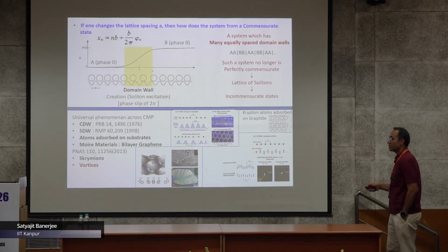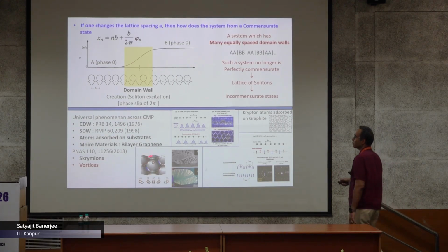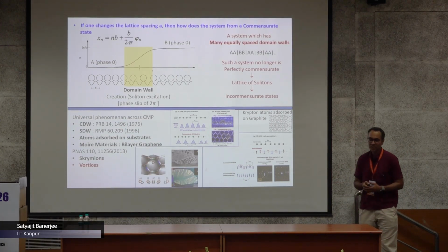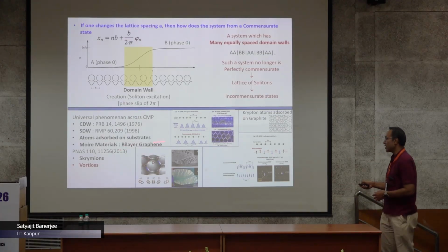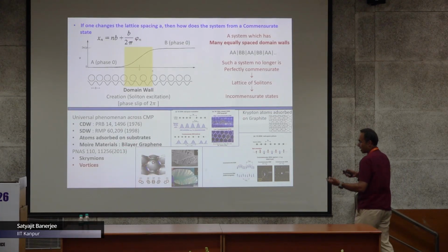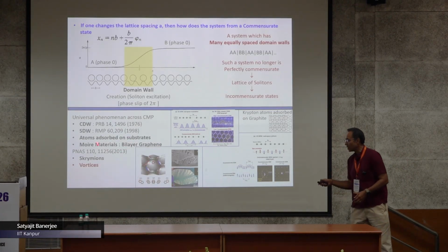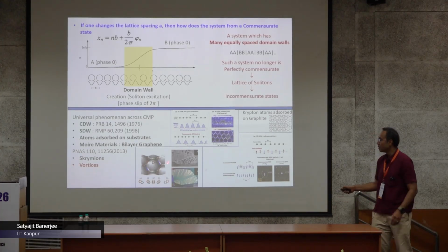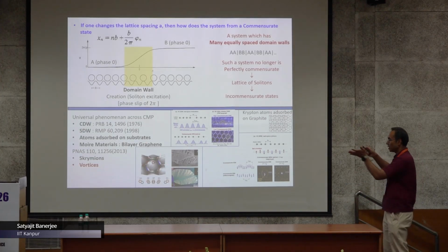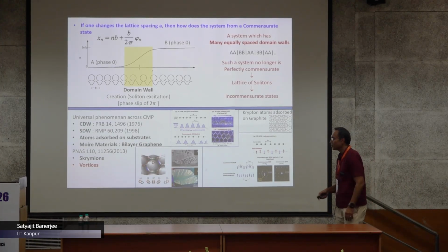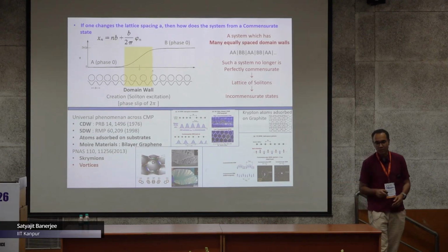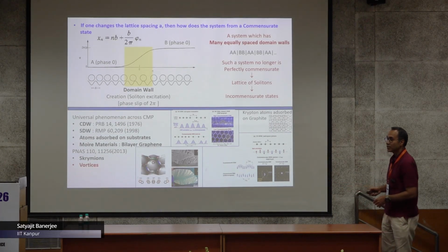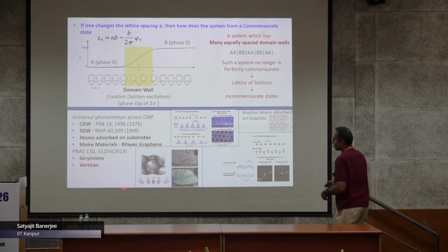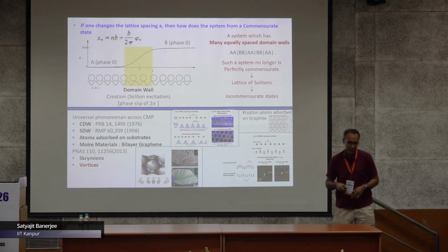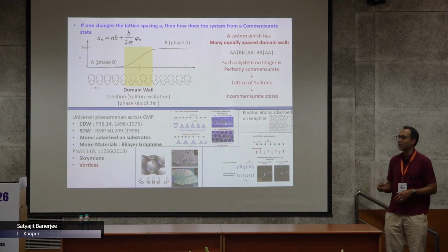Spin density wave states can be commensurate and incommensurate. You see similar features in atoms adsorbed on surfaces, moire structures, bilayer graphene, where people have seen domain walls between different types of commensurate phases inside these systems, in skyrmions, and finally in vortices.